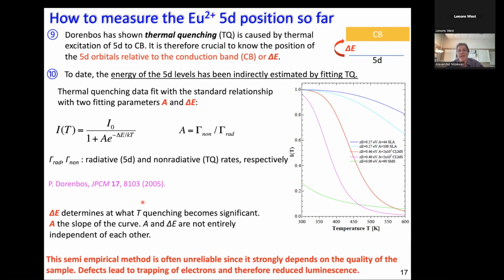Now, there is one disadvantage, other than that it's an indirect method. One other disadvantage is that most samples, especially when they are new and freshly synthesized for the first time, are not in a very pure phase. They have impurities, they have defects, and all these imperfections typically lead to a reduction, because electrons that travel in the material are lost. Therefore, when you have a loss in luminescence because electrons are trapped by imperfections, you can never be sure that this is really giving you the true delta E. It could in fact be that the sample is so imperfect that lots of electrons are captured by imperfections, and that leads to a reduction in luminescence as well. The method that I'm going to show you is independent of the level of impurities in the material.